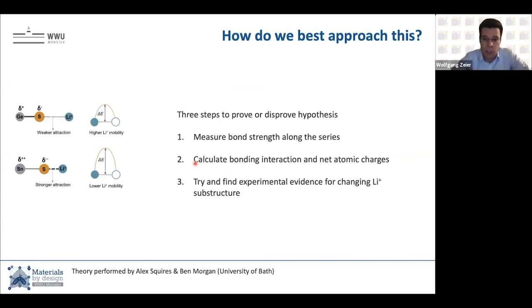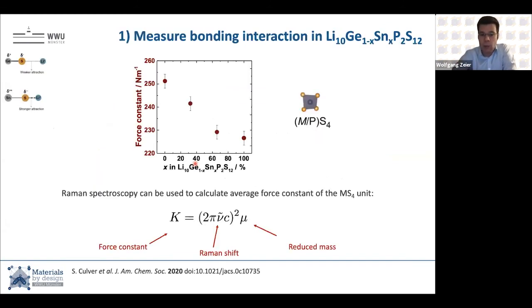The approach that we chose was to measure the local bond strength and average bond strength along the series, calculate these bonding interactions, and see if we can find experimental evidence that the lithium substructure is changing. All right, what did we do? The first thing you can do is collect Raman spectra, and these will give you the A1 or symmetric stretching modes of your polyhedra. If you know the Raman shift, you can calculate a force constant out of this by a reduced mass, and since the center of this tetrahedron is not changing, it's really just the sulfur that is the reduced mass.